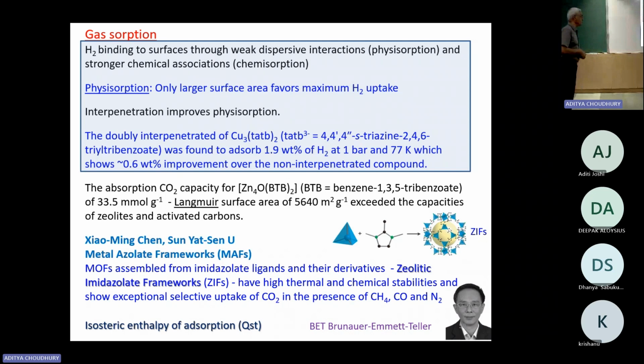We always think that interpenetration decreases absorption of gases. No, actually it improves physisorption. You'll be wondering how. It is not the empty space that is responsible. You would see from the experiments, doubly interpenetrated, this MOF was found to absorb 1.9% weight of hydrogen at 1 bar at 77 K. It shows 0.6% improvement over the non-interpenetrated compound. So the interpenetrated compound shows higher absorption. That shows that it's not the empty void space that is responsible.